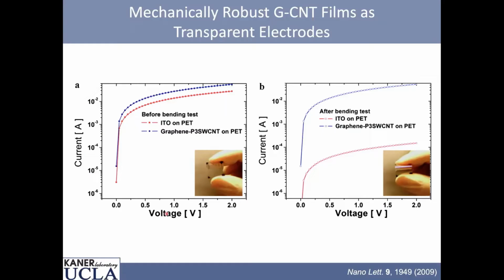And we're looking at a current voltage curve. So with our material, we get the same conductivity as indium tin oxide. So you can see that here in this IV curve. Now we put it on plastic, and the reason is then we can bend it.